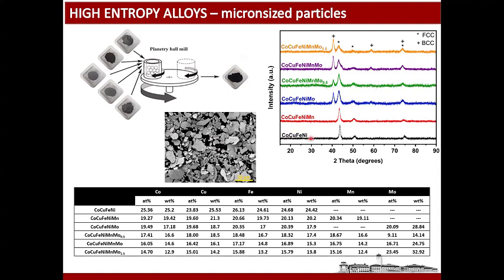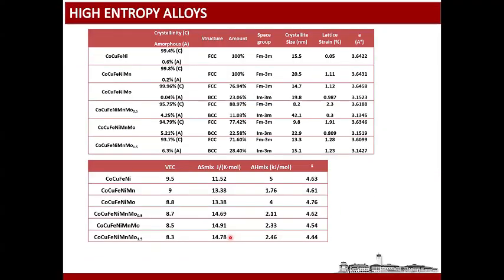structure actually. Cobalt, copper, iron, nickel has the FCC structure, but introducing molybdenum also produces the BCC structure, because molybdenum has the BCC structure. And then we started again with equimolar compositions, and what we get is close to the equimolar compositions, as you see in the table. So we ended up with the desired compositions after the ball milling. Of course, the introduction of the molybdenum changed the crystal structure. The structure without any molybdenum has the FCC structure, but introduction of the molybdenum introduced the BCC structure and then decreased the crystallite size of the FCC structure as well.